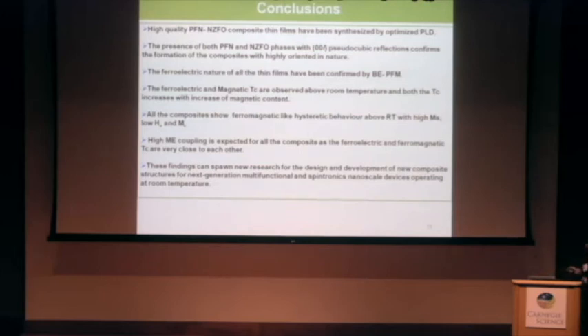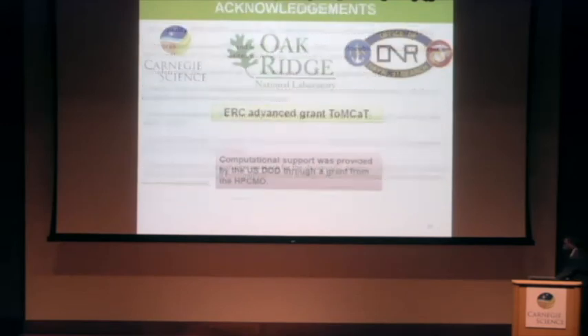In conclusion, we have synthesized high quality PFN and ZFO thin films, and the presence of both PFN and ZFO phases with 00l pseudocubic reflections confirms the formation of the composite with highly oriented nature. The ferroelectric nature of the thin films is confirmed by band excitation PFM. The ferroelectric and magnetic transition TC are observed above room temperature, and both TC increase with increasing magnetic content. All the composites show ferromagnetic-like hysteretic behavior above room temperature with high saturation magnetization, and high ME coupling is expected for all the composites as the ferroelectric and ferromagnetic TC are very close to each other.